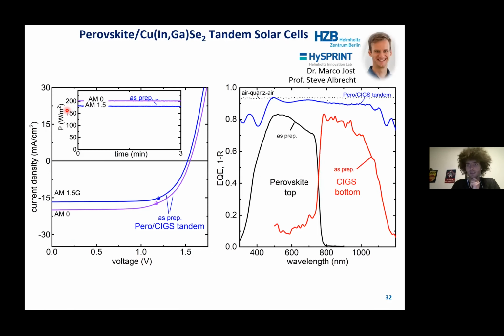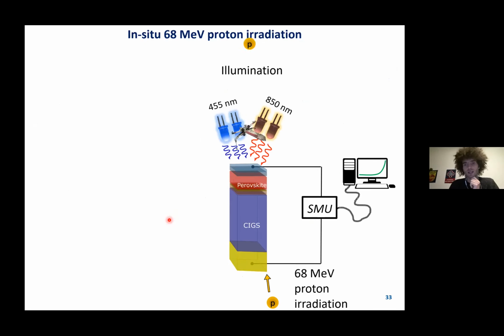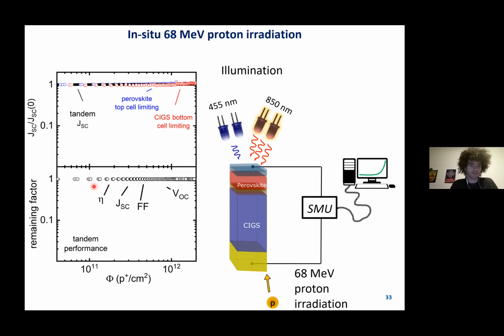And now I'm doing basically the same. I characterized these tandems before irradiation and then went to beam time to do an in situ experiment, again shooting protons while also studying the performance during irradiation. And I'm also doing the same experiment as before. So I reduce the intensity, for example, of the blue LEDs while maintaining the intensity of the infrared LEDs to be perovskite sensitive, and the other way around to be CIGS sensitive. And the results are now shown here on the left. So I don't see any degradation in efficiency, JSC, fill factor or VOC, and then of course also in the perovskite top cell limiting or the CIGS bottom cell limiting, we don't see any change over proton irradiation.